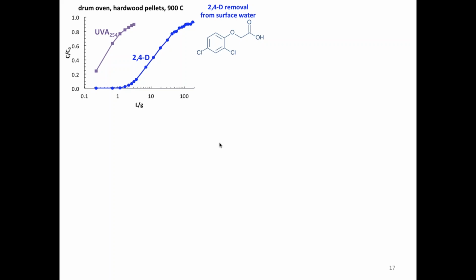And then I'm also showing a purple curve here for UVA 254. So this is basically the ultraviolet adsorbance signature of the background solution. This experiment here was done in surface water. The background organic matter component of surface water can absorb UV light at 254 nanometers. And the reason that we track that is because while it's very difficult and expensive and uncertain to try to measure trace contaminants like 2,4-D in the field in Thailand or Burma or wherever, it's easier to measure UV absorbance using a small field spectrometer.